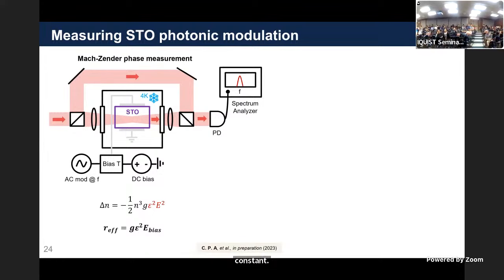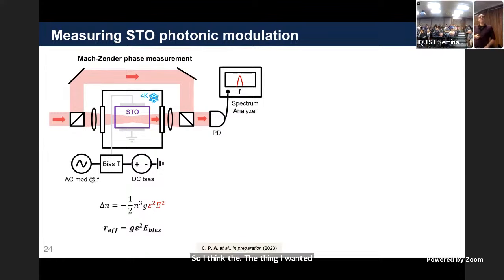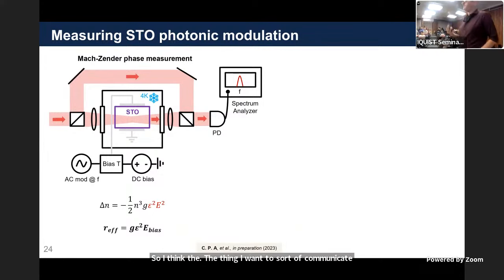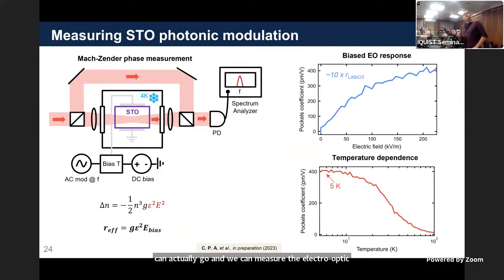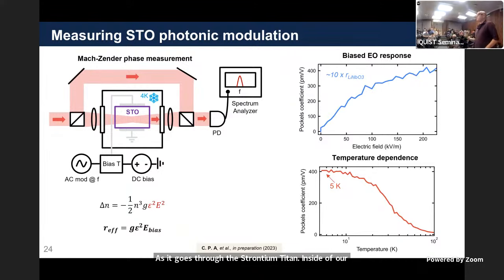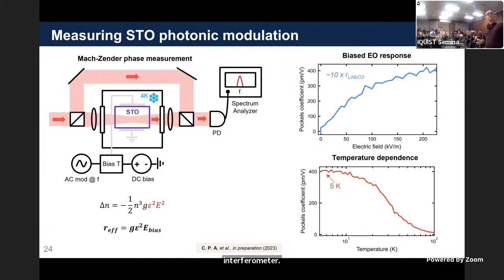So the thing I want to communicate next is that this is not just theory. We can actually measure the electro-optic nonlinearity of the system using a Mach-Zehnder interferometer, which basically encodes the phase shift of the light as it goes through the strontium titanate inside of our cryostat into an amplitude modulation through this interferometer. We can use that to measure this electro-optic coefficient.